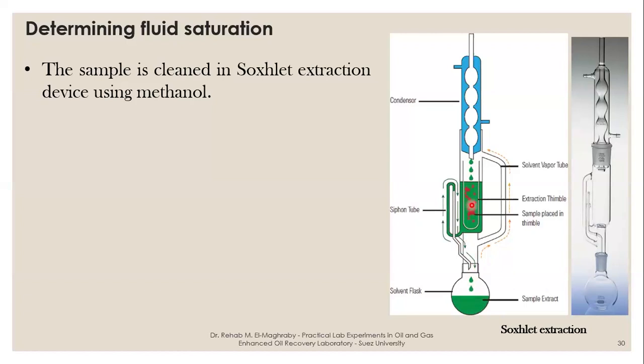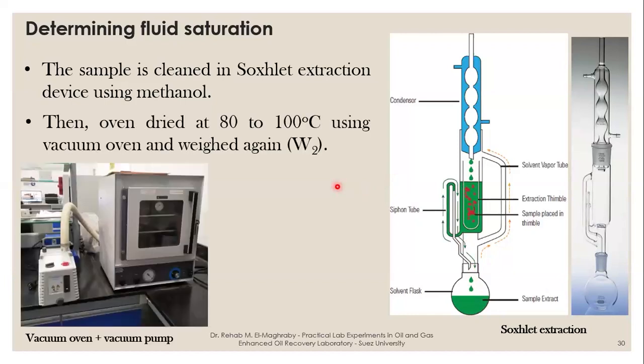So once we finish, it's like different runs. Once we have cleaned our core, we get it and put it in a vacuum oven. We want to make sure that the core is clean, there is no water in this core, there is no residue of solvent. We have to heat this core using an oven. But we are using vacuum because we want to heat it at lower temperature. Imagine that water will evaporate at 100 degrees Celsius at normal atmospheric pressure. But if you lower the pressure, the water will evaporate at a temperature lower than 100 degrees.